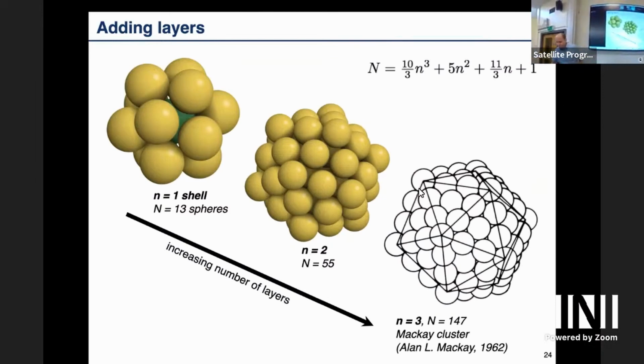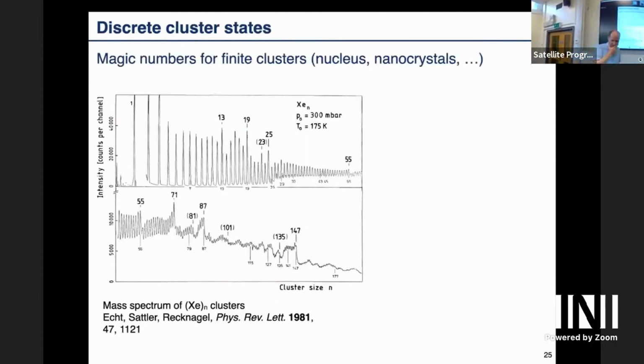Again, this is something super well known, and people studied that a lot already in the 80s and 90s. So this is again some pretty old work, from clusters of xenon atoms. You take xenon at low temperature, and it forms clusters in vacuum, and you do mass spectroscopy of these clusters as a function of cluster size, or mass essentially, and you do see these peaks.